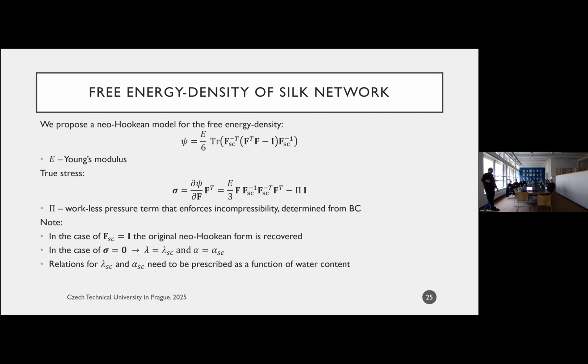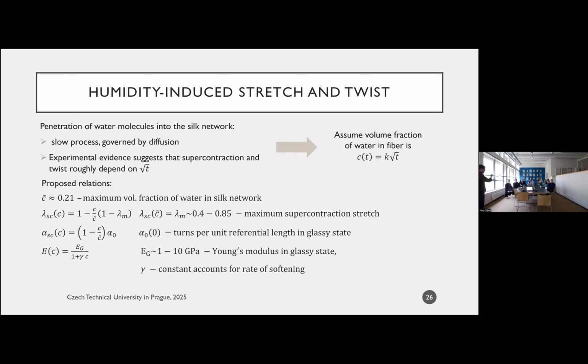And then you can see if there's no supercontraction, if there's no hydration, I just recover the original neo-Hookean form. In the case of a traction-free setting, where I just take this fiber and subject it to humidity, then the stretch is just a supercontraction stretch, and the twist is just a supercontraction twist. And if I want to be able to compare this to experimental findings, I need to prescribe relations for lambda SC and alpha SC. And so that's the next thing we went ahead and did.